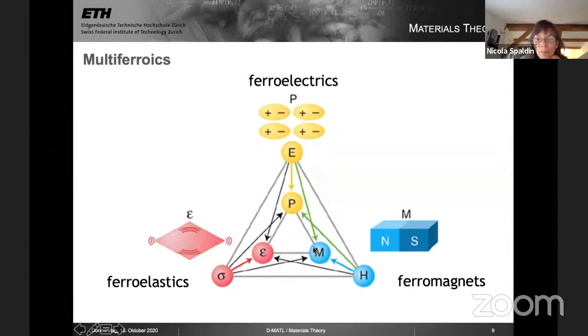Ferromagnetic ferroelastics also exist. The multiferroics that at the moment people tend to mean when they say multiferroic are this combination here, the ferromagnetic ferroelectrics, which are perhaps at the moment the most widely studied. The reason that the combination of these ferroic properties is interesting is that in addition to having the property switchable by its own conjugate field, so for example, polarization being switchable by an electric field, then in a multiferroic, one has cross couplings.